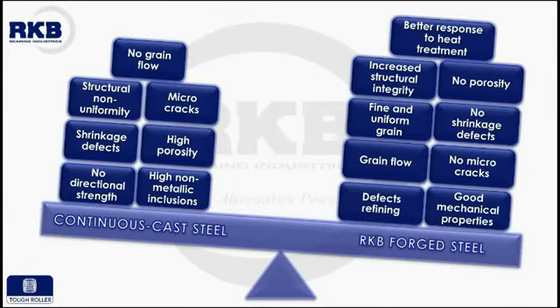This illustration shows the weighted comparison between the characteristics of continuous cast steel and RKB forged steel. As is evident, the specifications of the RKB forged steel are superior to those of continuous cast steel in the matter of chemical and structural integrity. In fact, by eliminating internal voids and gas pockets and dispersing segregations and non-metallic inclusions, the forging process provides our forged steel with superior chemical uniformity. This leads to a better temperability of rollers, which in turn leads to better mechanical properties and dimensional stability.